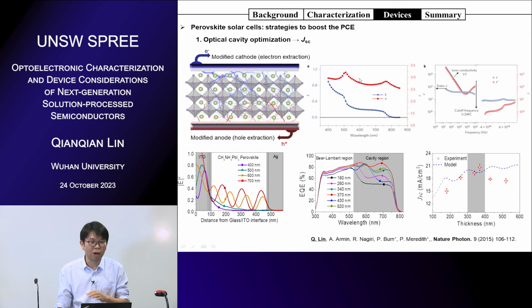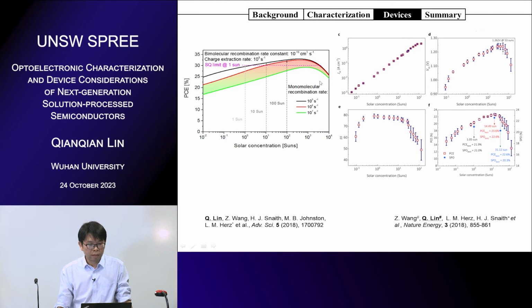We can talk a little bit more about devices we have done. If you have all the parameters like optical constants, you can use the n and k to do optical simulation of your real devices. Then we did some for perovskite solar cells in the beginning, and we also designed some concentrators for solar cells, because solar cells will normally work better under high light intensity. So we increase light intensity to 10 suns, 100 suns, and the efficiency will go up because the open circuit voltage can easily go up. So these are all from the understanding of the charge transport.